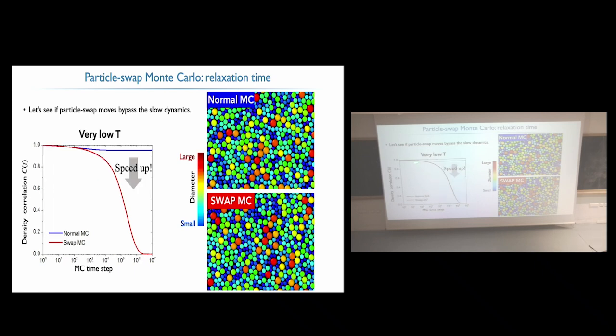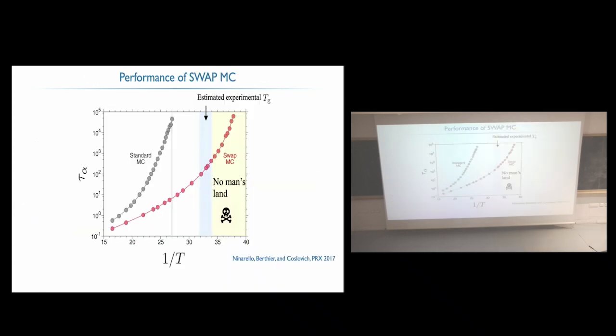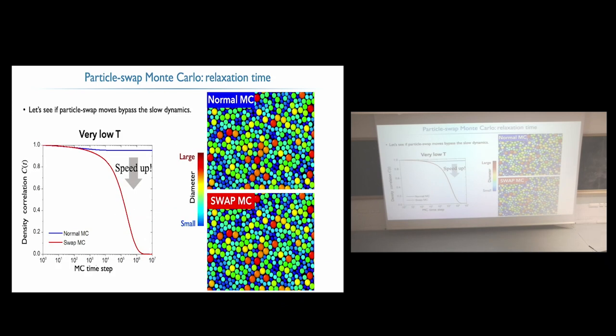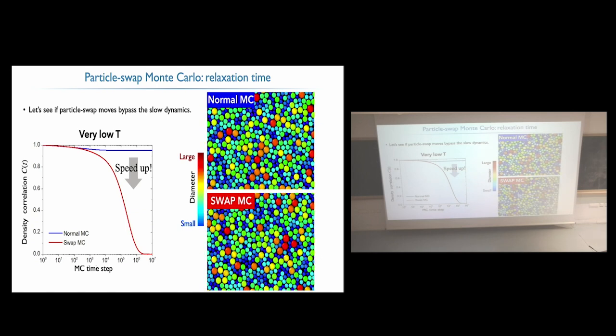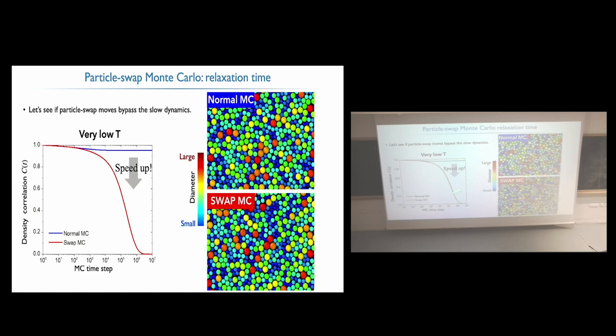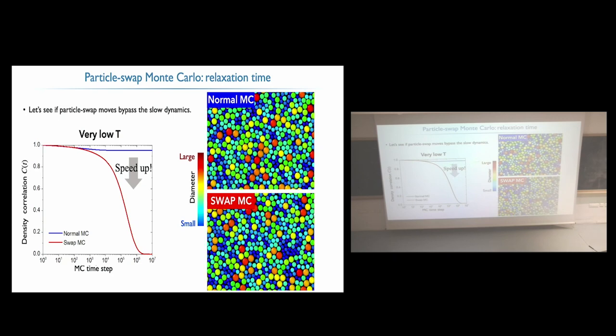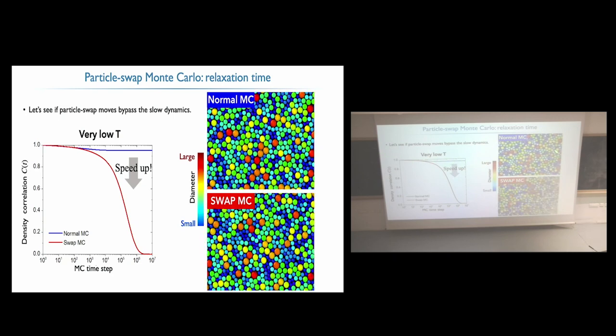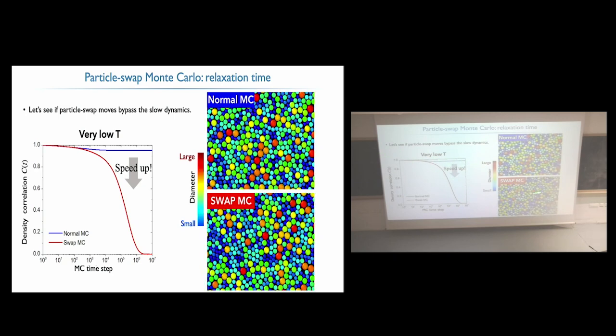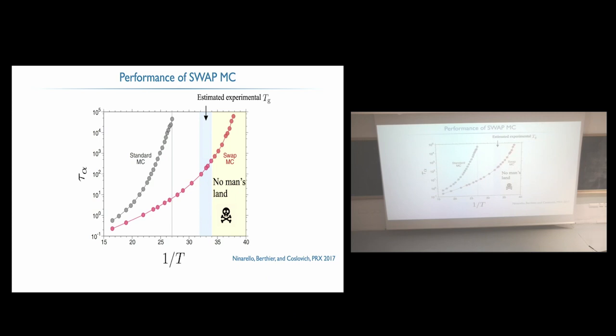If we go even below, so very, very low temperature, close to TG, if you were to run the normal MC, you would get a plateau, so really nothing moving. Really nothing again. And now you add swap, and boom, you can really relax. So something that became impossible to sample, where you basically get stuck in the same place, really relaxes. So this is quite dramatic. And this is summarized here.